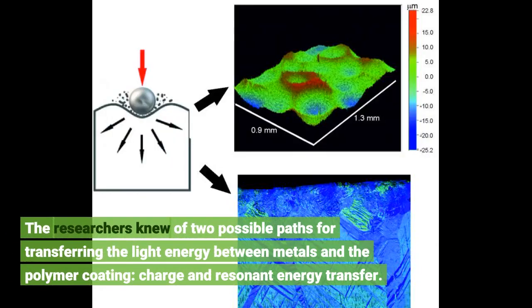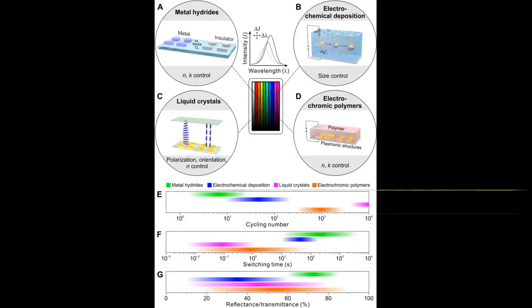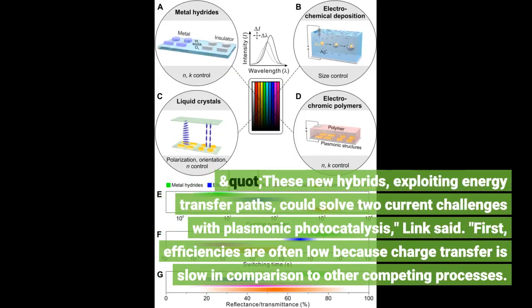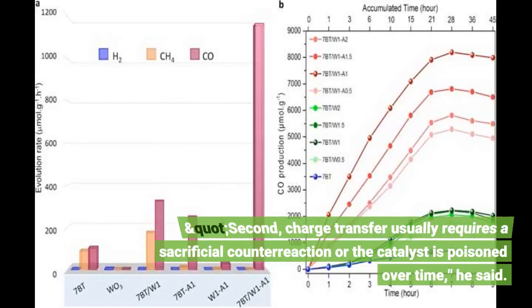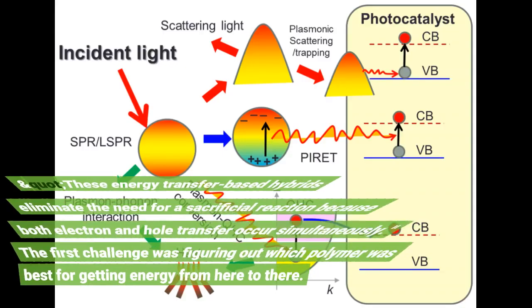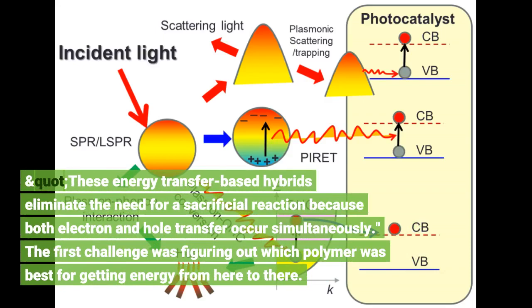The researchers knew of two possible paths for transferring the light energy between metals and the polymer coating: charge and resonant energy transfer. These new hybrids, exploiting energy transfer paths, could solve two current challenges with plasmonic photocatalysis, Link said. First, efficiencies are often low because charge transfer is slow in comparison to other competing processes. Second, charge transfer usually requires a sacrificial counterreaction or the catalyst is poisoned over time, he said. These energy transfer-based hybrids eliminate the need for a sacrificial reaction because both electron and hole transfer occur simultaneously.